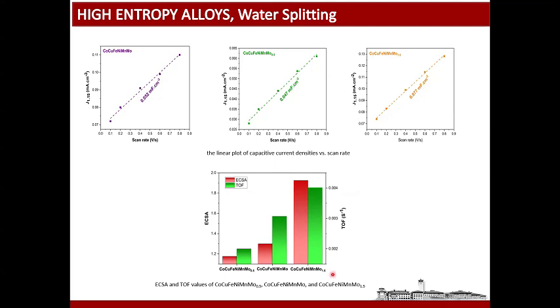So the molybdenum 1.5 composition has the highest turnover frequency. This is showing that the intrinsic property is also good. So independent of the area and the amount of material, intrinsically it's a good electrocatalyst. And electrochemical active area is also increased by introducing molybdenum into the structure.